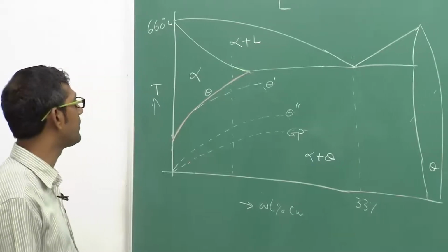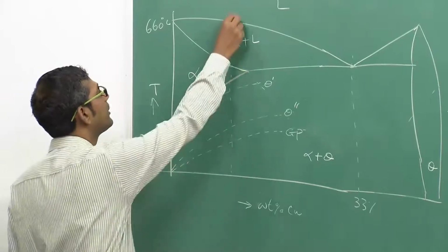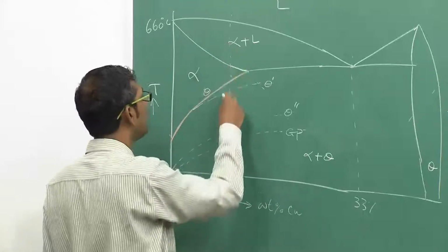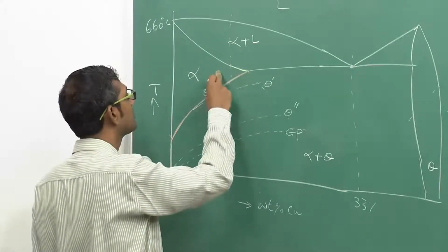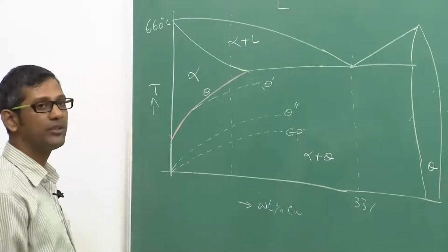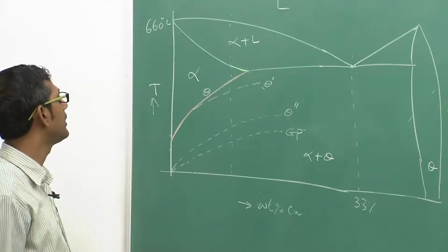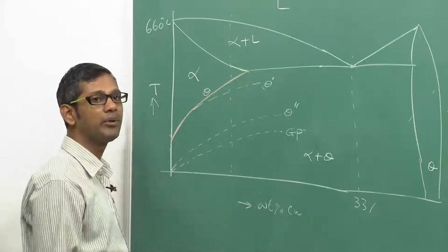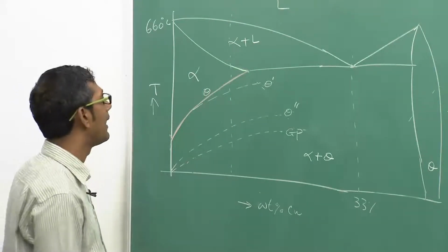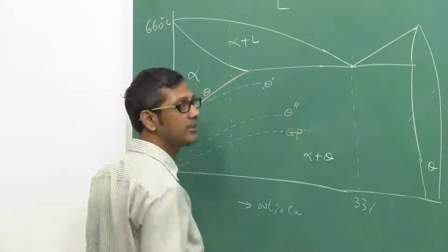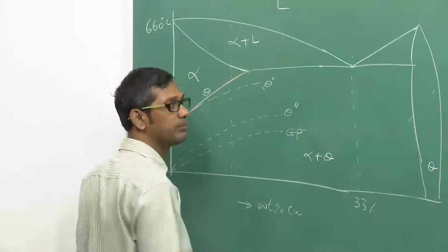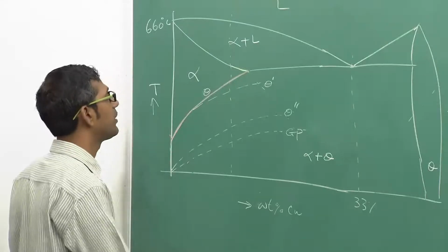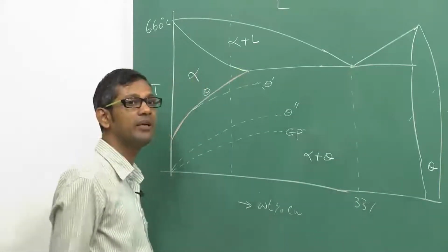It is very difficult to stop that, because when they are continuously solidified from the liquid, although it looks like this will have a single alpha phase, because of the coring during the continuous solidification, there will always be some liquid left over at the end. And as the copper is rejected into the liquid, this liquid will have a very high copper concentration. That is one of the problems in these alloys. Because of that, some eutectic will inevitably be present.